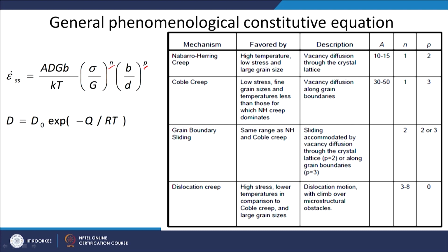So you can see that for Nabarro-Herring creep, it is favored by high temperature, low stress and large grain size, as I was telling you. So at very low stresses and large grain size you will have Nabarro-Herring creep. Vacancy diffusion through the crystal lattice, A will be in the range of 10 to 15, the exponent n is 1, which means it has a linear relationship, and the grain size exponent is 2, as we have just seen.